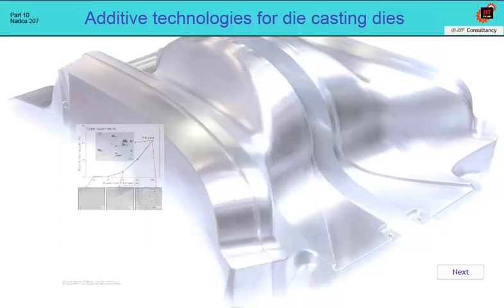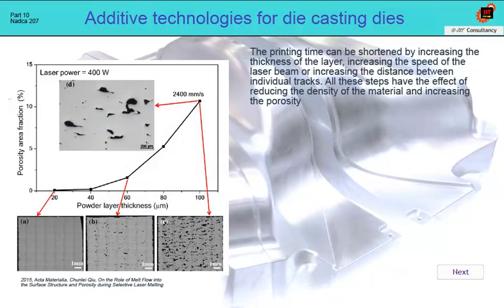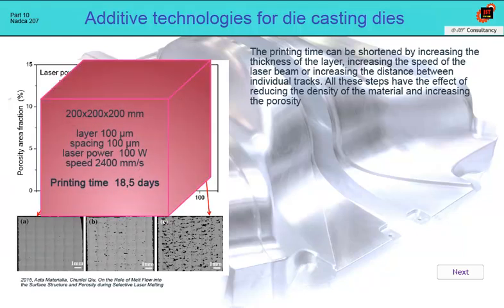The strategy of the printing will fundamentally influence its economy. If we were to try to print a cube with a side of 200 millimeters and a weight of approximately 63 kilograms, with a thickness of individual layers of 100 microns, the distance between the tracks also 100 microns, then the printing time would be 18.5 days. At an estimated hourly rate of the printer of 100 euros per hour, the price of printing would be 44,000 euros. The print density will be somewhere around 98%. We don't know if it's acceptable quality, but it's definitely an unacceptable price.